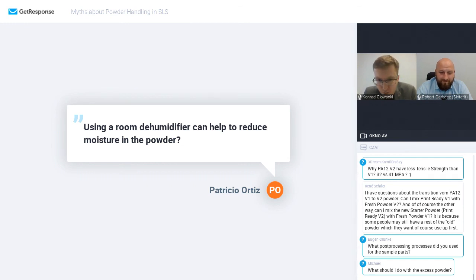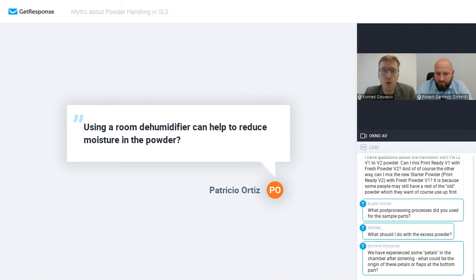Yes, like Patricio Ortiz said, using a room dehumidifier can help to reduce moisture in the powder. It could in some way help prevent adding moisture into the powder, but it will not remove it back. So we have a process to remove it. There are situations when you could use a special process to remove the moisture. The most important thing is that the printer and the whole process shouldn't work below 45% humidity. So a completely dry climate room is not recommended.